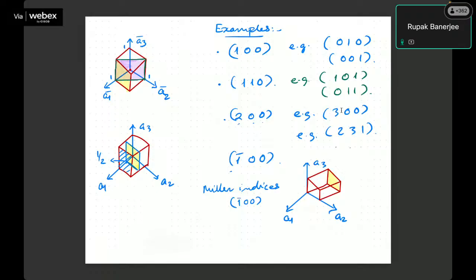So if you have a higher index for H, it means that the plane is actually closer in terms of its distance to the origin. Okay, so this thing is very important to know. Typically, when you have 1 bar 0 0, which means that you have a1, a2, a3 axes, but instead of having 100, which is in this direction, you are having it in the opposite direction. As you can see, this is probably not a great figure, but I hope you understand that a1 is intercepting at -1, and this plane is parallel to the a2 a3 axis. So this tells me it is a 1 bar 0 0 kind of plane.